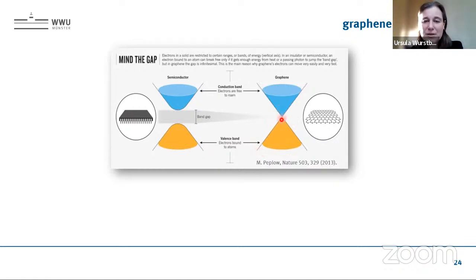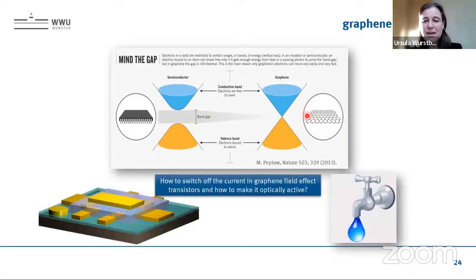And actually, in graphene there is no band gap, so with that you cannot really turn off such a device. You can make an analogy to a leaky water outlet, meaning there are always charge carriers dropping through in the circuitry of graphene. And that's a little bit the difficulty for graphene here.